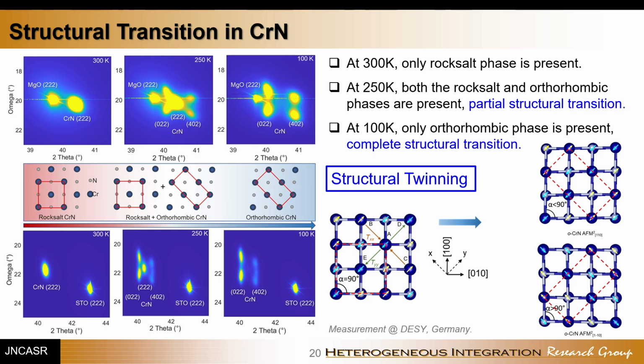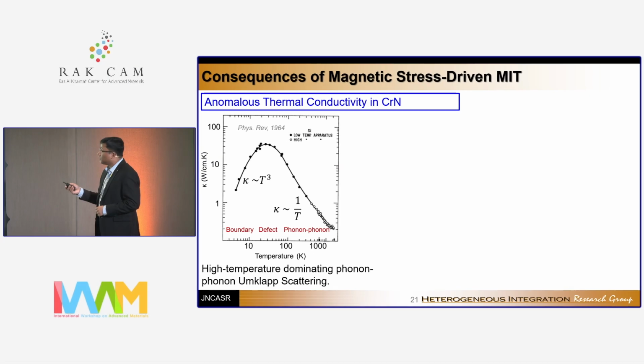Because of the symmetry in the magnetic stress, in chromium nitride, in one case, the distortion basically opens up the structure slightly from 90 to 91, 92 degrees. In the other case, it contracts from 90 to 89 degrees. So that is basically the demonstration of the chromium nitride metal insulator transition and the mechanism of the chromium nitride metal insulator transition.